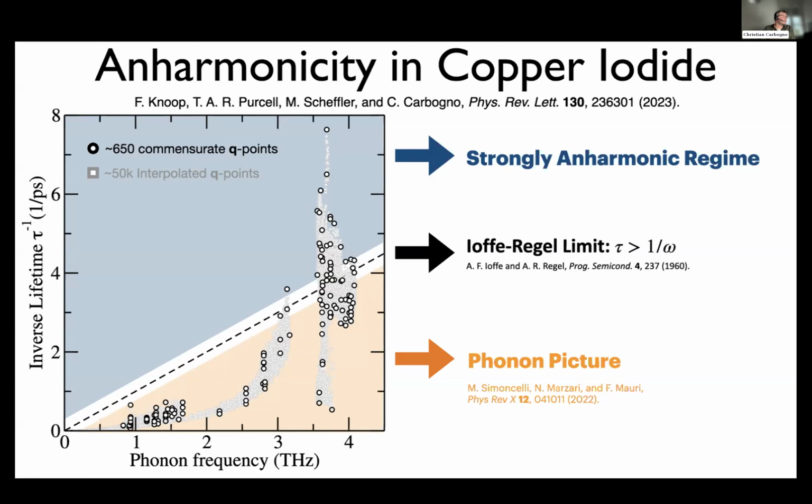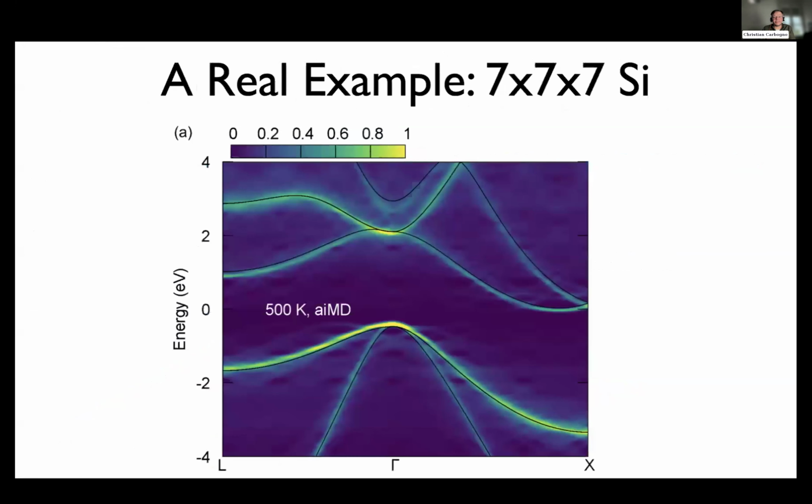And you can in principle do the exact same for electronic transport. Let me go back. Here, for instance, for silicon, the relaxation time or the quasi-particle lifetime would be the width of this distribution here for the electrons. So you see here we have a larger width that implies a shorter lifetime because width and lifetime are related by 1/.